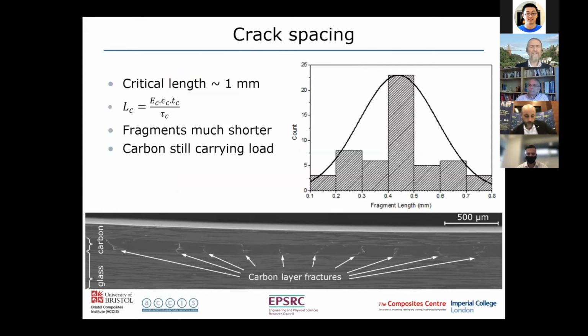Now, if you look at those, you can consider this a little bit like a fragmentation test. In tension, you have a critical length of a fibre, or this can be applied at the ply level. And if you work out the length required to get load into the ply by shear, then you can work out this critical length, which is a function of the modulus, the compressive strain to failure, the thickness of the ply, and the interfacial shear stress.